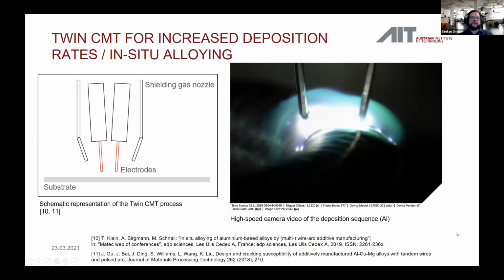At the moment we are experimenting with twin cold metal transfer for increased deposition rates. In this process, two electrodes are used at the same time within one welding torch. This allows to increase the deposition rates, and in future, maybe it can also be used for in situ alloying when two wires with different chemical compositions are used at the same time. So here again, the deposition sequence, now using double wires. You can also see from the video that the wall thickness is increased. So in fact, you can double the deposition rate.